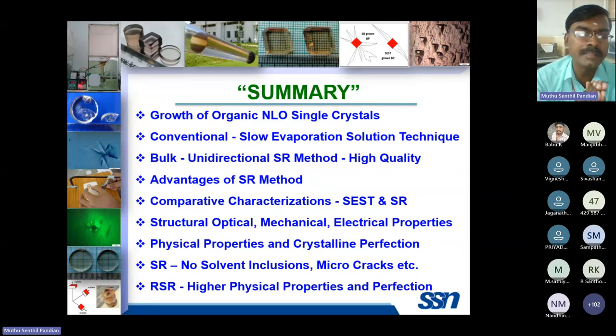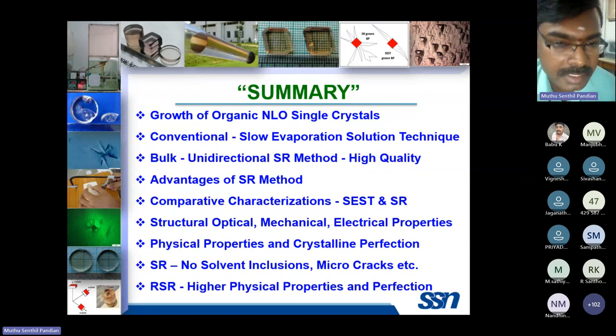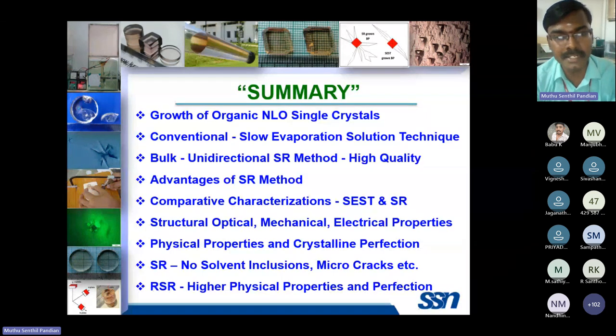Under identical conditions, we have compared the RSR and conventional SR method grown crystals. The RSR method grown crystals have higher optical transmittance, higher mechanical stability, higher dielectric permittivity, higher optical homogeneity, and higher crystalline perfection compared to the conventional SR method grown crystal. So this RSR method grown crystal is more suitable for any kind of optical or ferroelectric application compared to the other two methods.